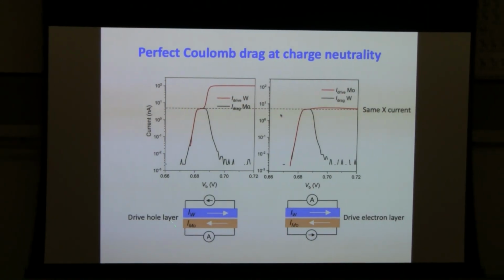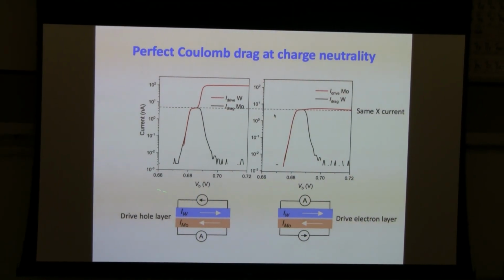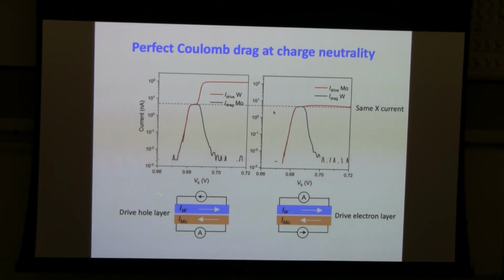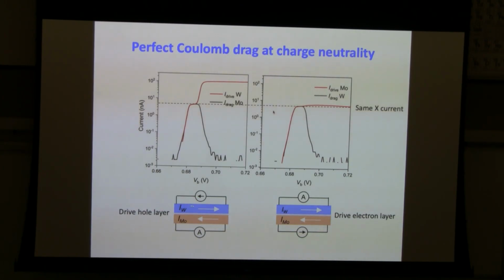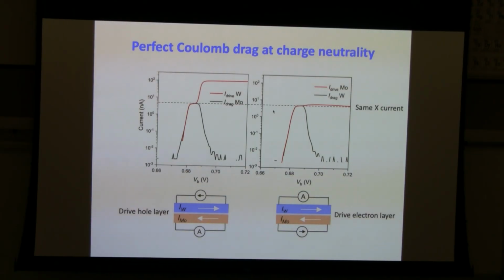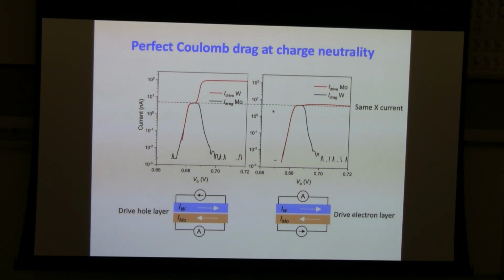So you can think of it that each of these contacts to the hole and the electron, this pair of contact is an exciton contact. So you have one exciton contact here, two exciton contact. You can flow an exciton current, but then there is some chemical potential drop at the contact. But if we can actually put four of these contacts here, and we measure basically the displacement field gradient in each of these contacts. Let's say we add two other probes. We measure the interlayer voltage difference at this location and also measure the interlayer voltage difference at this location. And if this voltage difference is the same on the two locations when there is an exciton current flow, that should be a definitive proof of exciton superfluid. So we know the answer, but we failed to do it yet.